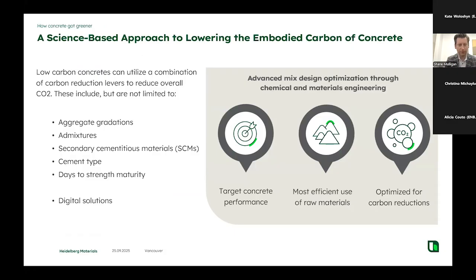Looking at different novel admixtures or different combinations of admixtures to help either reduce the water demand or increase the strength of the concrete mixes is another strategy that's becoming more typical. And there's a lot of great research that's going on in that space to help strengthen the concrete and reduce the cementitious contents. Secondary cementitious materials, that's looking at things like fly ash, waste product from the coal industry, or slag, which is a waste product from the steel industry.